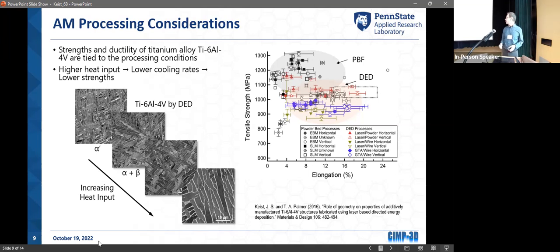What we have realized is that this area is tied to how you're processing your components. This is an example for titanium, where if you increase the amount of heat you use when building your components, you change the structure. And that structure directly impacts your properties. So it's critical to understand how that impacts your process. For instance, if you need to make sure you're getting tensile strengths above 1,000 megapascals and elongation above 12%, you need to understand how to get that process under control.